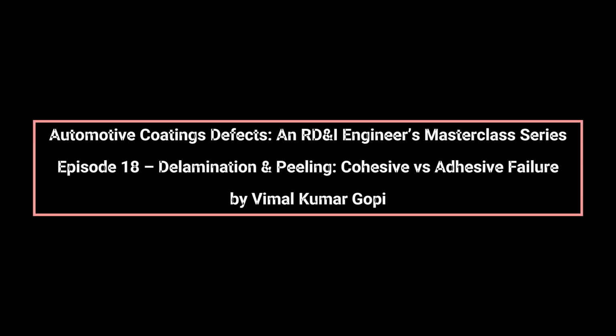Solvent behavior during application strongly influences delamination risk. Trapped solvents weaken interlayer cohesion and plasticize films unevenly. During service exposure, these solvents slowly migrate, creating voids or stress concentrations that trigger peeling. Conversely, aggressive solvents can overattack underlying layers, creating a weak, swollen interfacial zone that later collapses. Proper solvent balance ensures controlled swelling for adhesion without long-term structural damage.